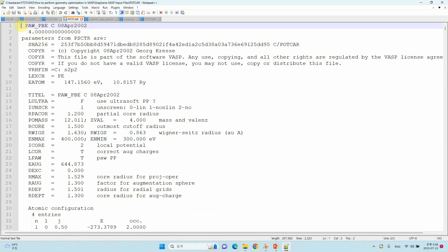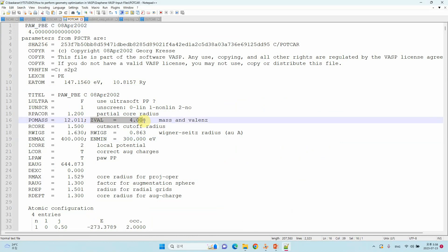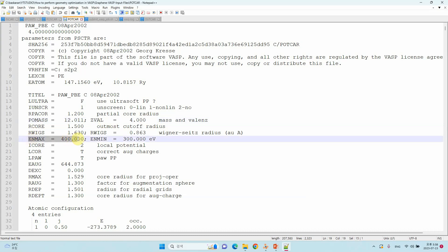Then the POTCAR file — this is the POTCAR file for carbon. Here you can see the ZVAL, which is the number of valence electrons of the atom. This is very useful for doing a Bader charge calculation. I also showed ENMAX=400 here — this is the maximum energy cutoff and ENMIN=300 is the minimum. You need to set ENCUT to the maximum energy cutoff of your system, which is why we use 400 in the INCAR.